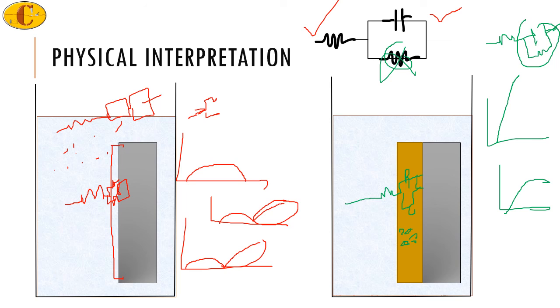Further, if you see that the coating has now completely degraded and the metal has now come in contact with the electrolyte, in this case now you will have a resistance for electrolyte, a parallel capacitance, a resistance, and in this resistance you'll have a second inset parallel circuit. So this inset parallel circuit indicates that the electrolyte has gone through these pores and reached the surface of the substrate and begun the corrosion of the substrate.